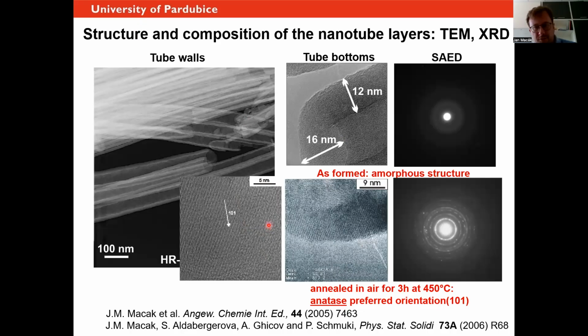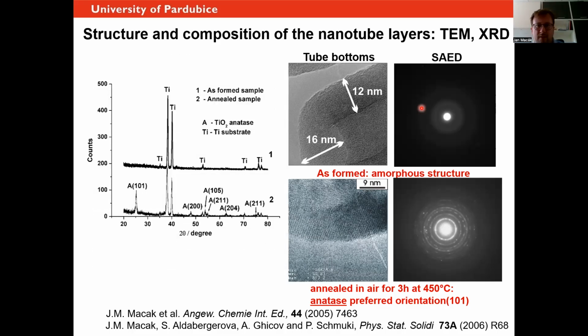And in terms of composition, if you do XPS, you will find out that you have always, of course, titanium dioxide. You might also have some carbon and also some fluorine. And the carbon actually comes from the impurities from the electrolyte, because the electrolytes are typically carbonaceous, like ethylene glycol. And the fluorine comes from some traces of the ammonium fluoride. But it's possible to get rid of it.